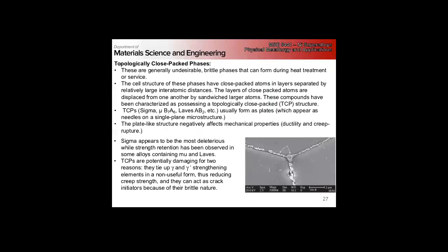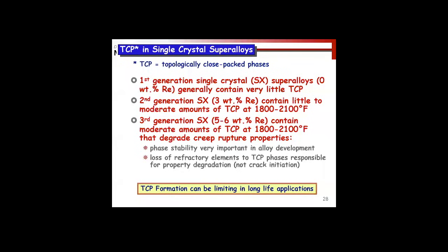So we want to avoid forming these TCP phases at all cost. The difficulty is the things that we're doing to improve our creep strength also increase our susceptibility to forming TCP phases - the same things that are good for creep also tend to want to form these TCP phases. So we have to be very careful about studying phase stability very carefully, and the long-term phase stability during service, very carefully in superalloy development.